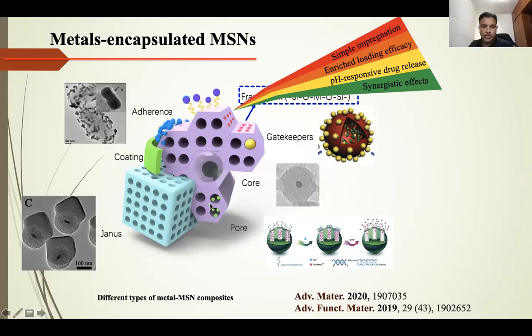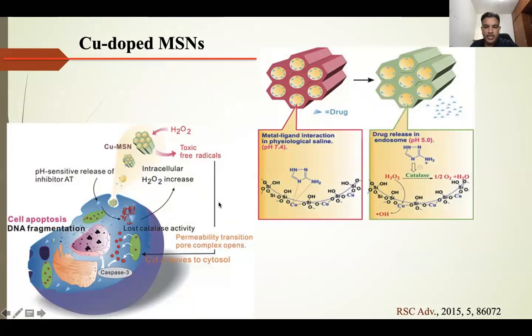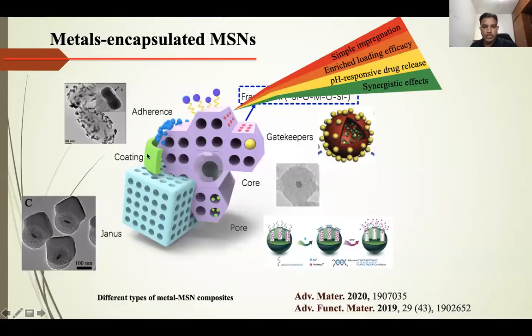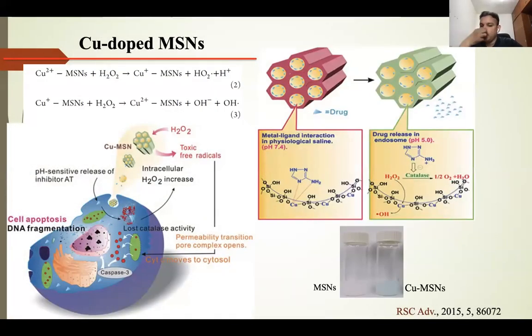So this is how the nanoparticles can be loaded inside as well. But my area of research interest is about conjugating the framework. Why my thought was changing the framework, because the silica has some sort of degradation problems and compatibility problems which are harmful to the cells. So I decided to change the framework of the silica, so that it can easily load the drug, be easily degradable, and have compatibility by reducing the silica density inside the particle.